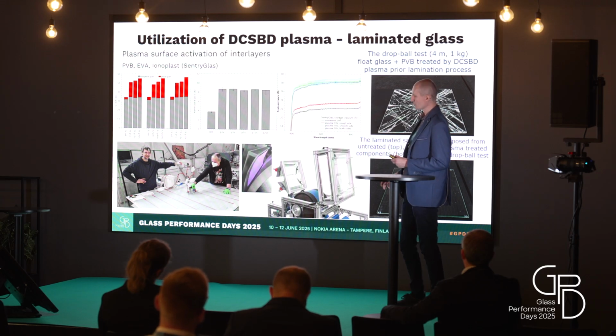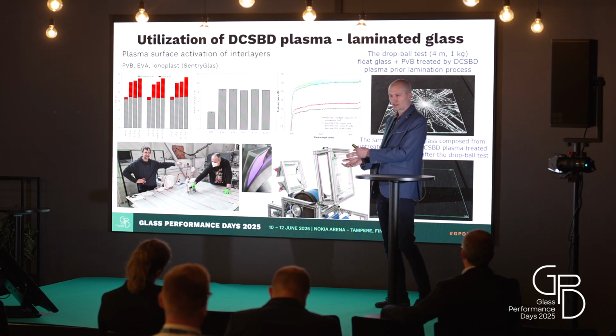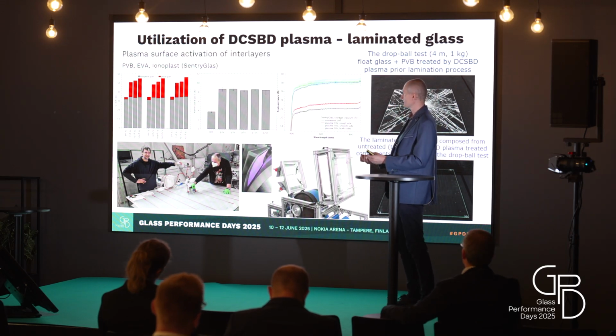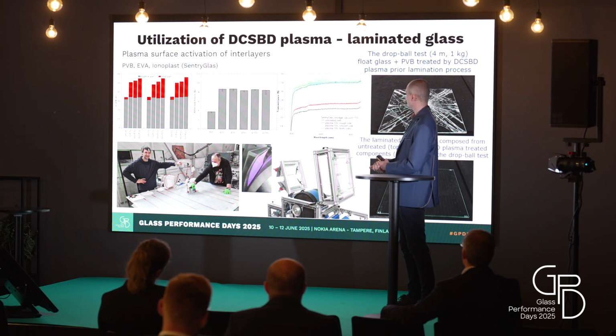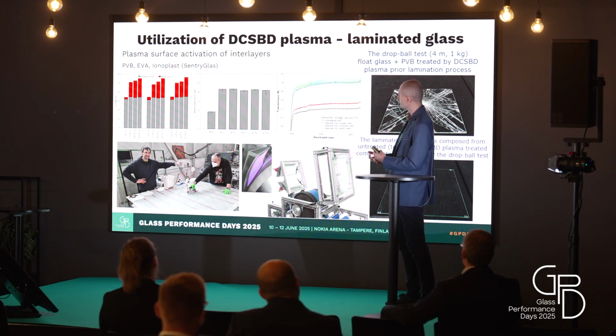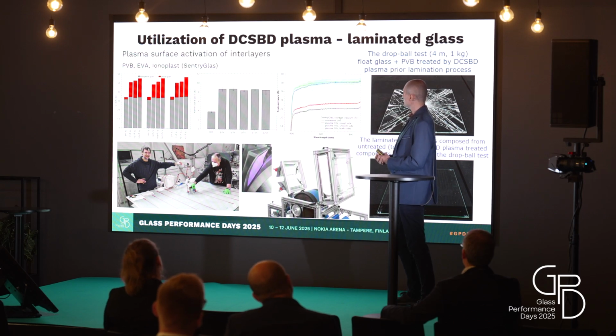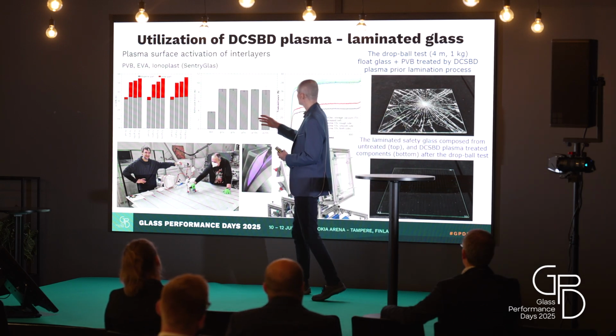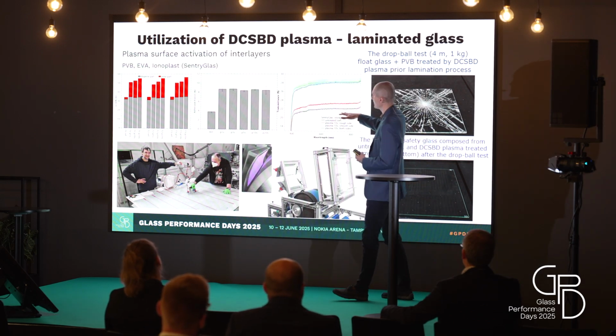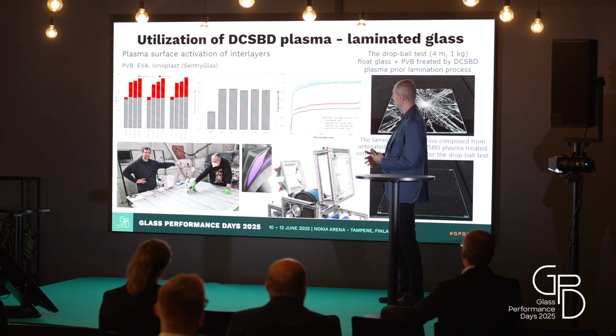It's also possible to treat not only the glass, but also the interlayers, for example. In that case, we can also do some cleaning. We can change the surface-free energy. We increase the polar component mainly. We improve the adhesion force. What is very important is that we didn't change the optical parameters of the interlayers.